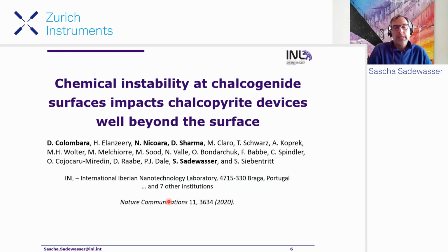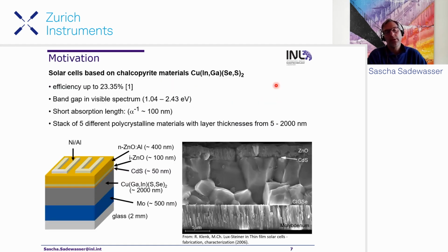So with this, I come to the first example. This is on copper indium gallium diselenide solar cells, and maybe a quick introduction and motivation for these materials. So they are a thin film solar cell technology. The absorber, as opposed to silicon, where you have about 200, 300 micrometers of absorber, here you have 2 microns of absorber, so 100 times thinner. This is because it's a direct semiconductor and therefore absorbs light very well.